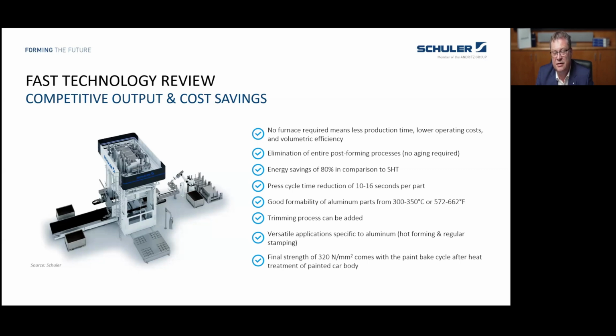So the result of the investigations of the Imperial College was about 80% in comparison to the other heat treatment processes for aluminum. The press cycle is pretty fast due to the fast heating. We have, depending on the size and the blank thickness, 10 to 16 seconds cycle time per part. The process actually delivers extremely good formability of the material and especially a very good repeatability.